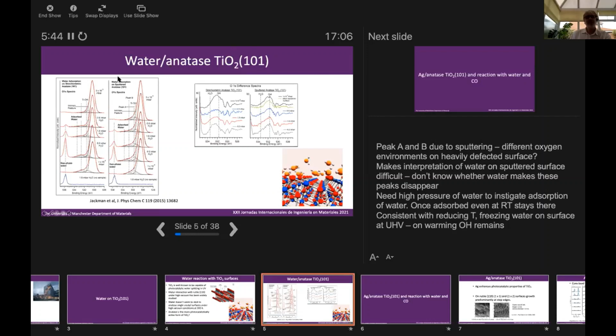And here, this is a sputtered surface. So what we did to this one is we used a cluster ion source and we gently etched the surface, and this will produce oxygen vacancies at the surface. Okay. For the clean surface, we see this small additional peak here due to the presence of subsurface oxygen vacancies. So in anatase TiO2 101, it's known that the vacancies sit subsurface, and this is believed to be one of the reasons that the anatase has a higher catalytic activity, because when the reactants interact with the surface, they don't heal the defect. The defect remains there below the surface, but you can still get the charge transfer occurring. So we get this additional shoulder on this side due to these subsurface vacancies.